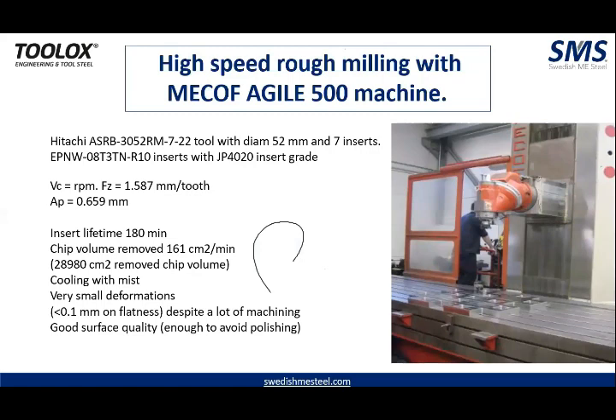High-speed milling is also possible, as you can see. The insert lifetime is 180 minutes in this. The volume of chip removed is 160 cubic centimeters per minute. Even when you do extensive machining, the deformation is very small, less than 0.1 mm on flatness. Even after your extensive machining, the surface quality is so good that even additional polishing would not be required.